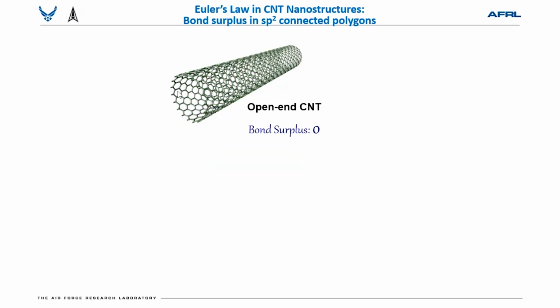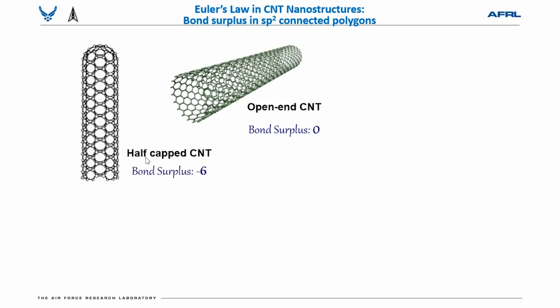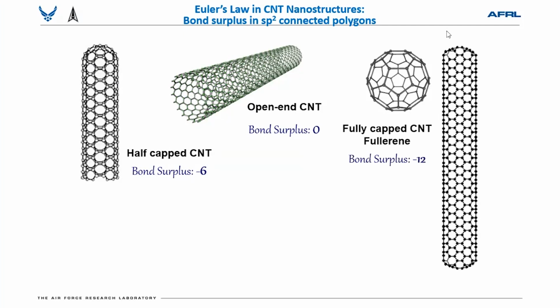All carbon nanotubes in this case are 6-member rings. And then when you look at the other geometry, half-capped CNT, meaning this end is capped, then you no longer have only 6-member rings. There are some 5-member rings and so forth. And you need 6 of them. So that brings bond surplus minus 6. If you do a fully-capped CNT or fullerene, because of the same concept of 7-member ring accommodation, 5-member ring accommodation to 6-member ring, the bond surplus becomes minus 12.